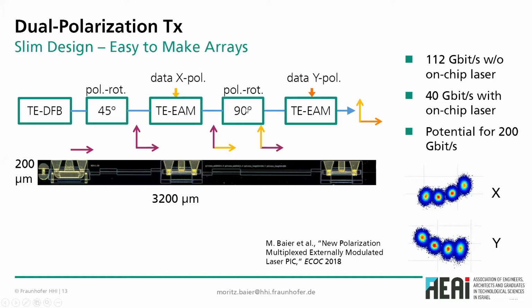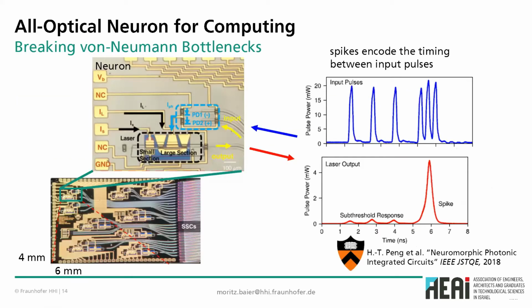And now the next polarization rotator, which rotates by 90 degrees, effectively swaps the TE with the TM component. And so the last EAM, the last electro-absorption modulator, can now modulate the remaining continuous wave fraction of your carrier. And so this orange data signal will now be imprinted on the remaining purple arrow. And so you have a dual polarization signal exiting your chip, which we show here with 112 gigabit per second gross data rate, without ever having to split or recombine optical signals, as is normally the case in dual polarization schemes.